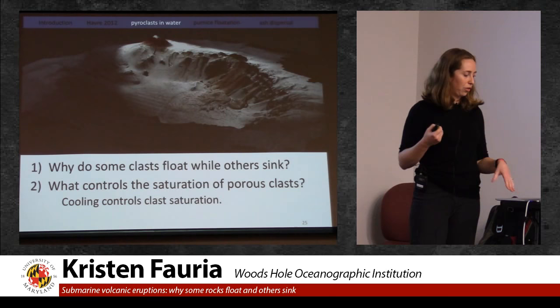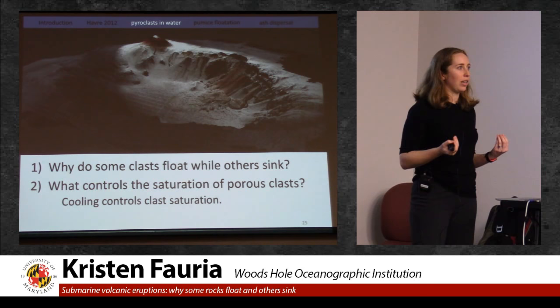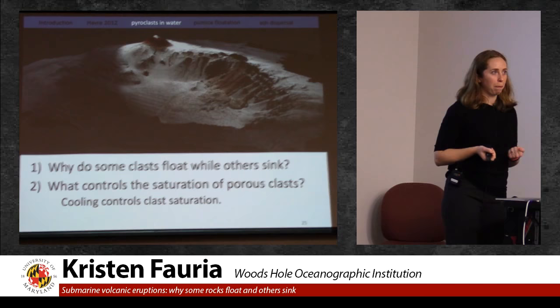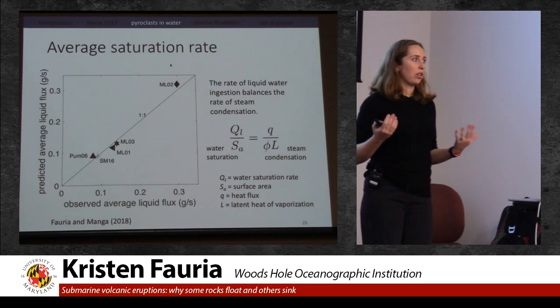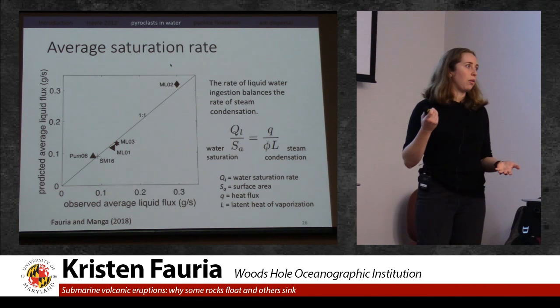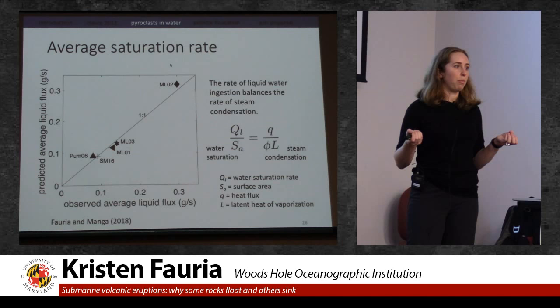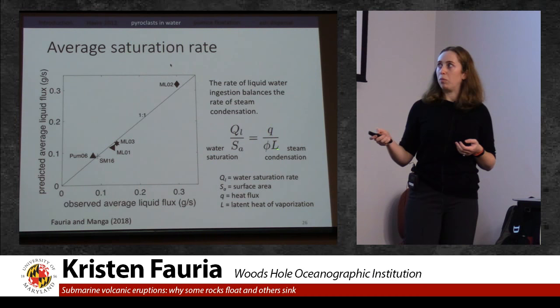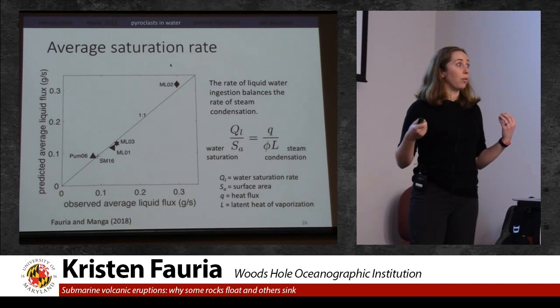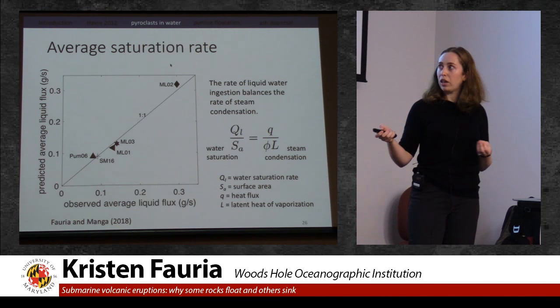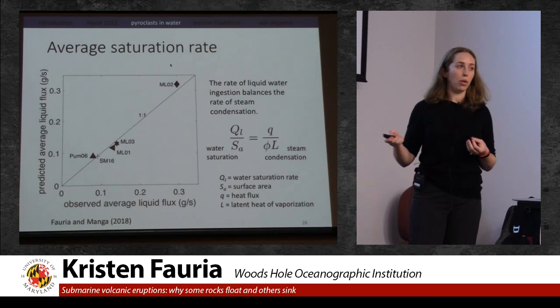And so I want to go now to the first question: why is it that some clasts float and others sink, in particular related to the Havre eruption? Well, using our new saturation model for porous clasts, or cooling and saturation model, we can predict the rate at which liquid water goes into clasts, because the rate of water ingestion is balancing the rate of steam condensation. So here is our cooling rate divided by latent heat of vaporization, and a porosity is proportional to the rate of liquid water flowing into the clast. And we validated this at least for the smaller clasts in our experiments, where this is the predicted flux to the observed flux, and that's a one-to-one line.